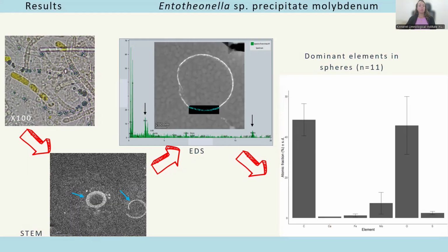And this is the central result of the study. Entotheonella cells contain intracellular molybdenum-rich spheres. The FFT analysis, however, did not detect a clear crystalline signal from these spheres. This suggests that the material may be amorphous, disordered, or mixed phase that is difficult to resolve by this method. I will phrase this carefully. These results support intracellular molybdenum accumulation by Entotheonella, most likely through a biologically induced mineralization process.